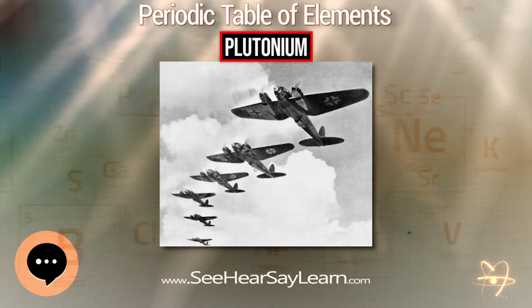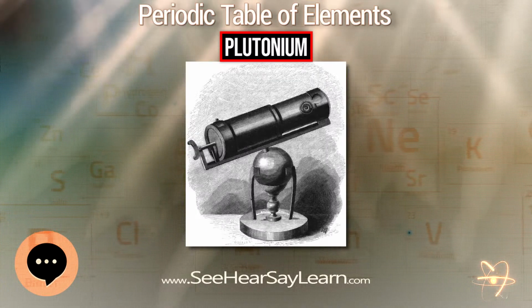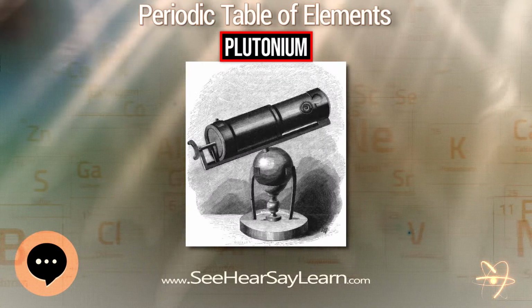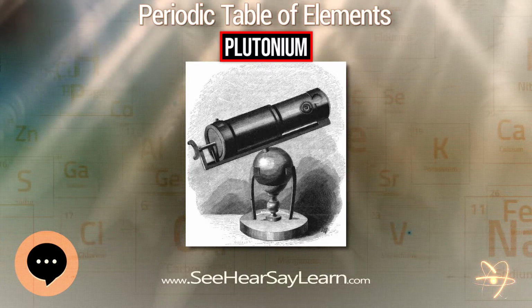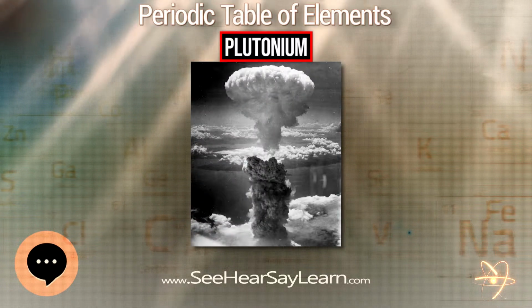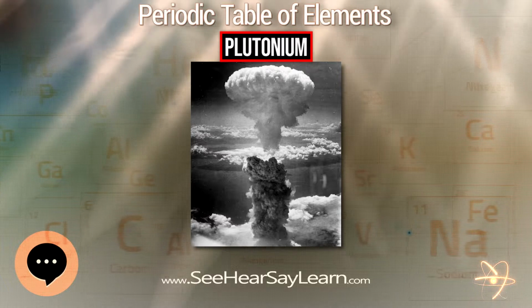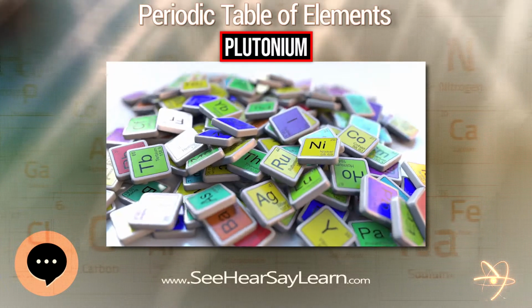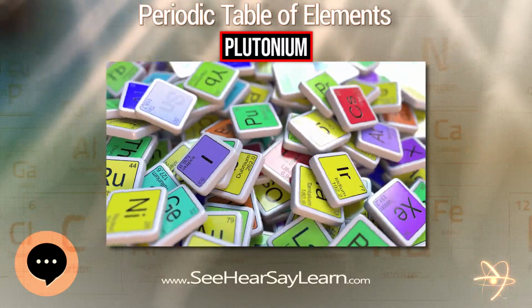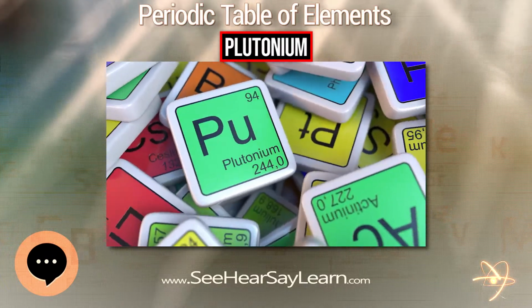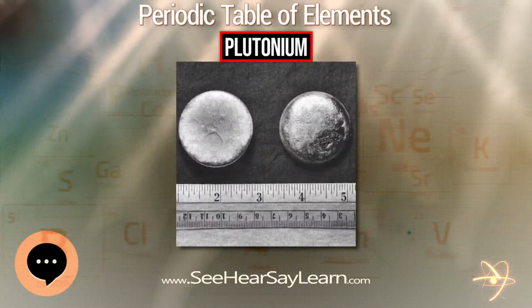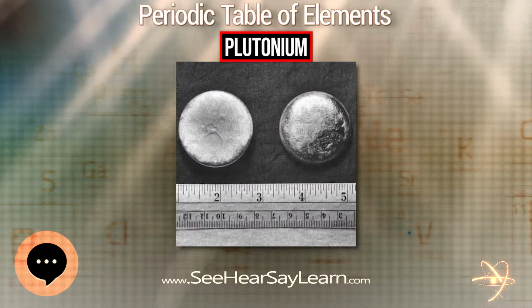Plutonium in the delta form normally exists in the 310 degree C to 452 degree C range but is stable at room temperature when alloyed with a small percentage of gallium, aluminium, or cerium, enhancing workability and allowing it to be welded. The delta form has more typical metallic character, and is roughly as strong and malleable as aluminium.